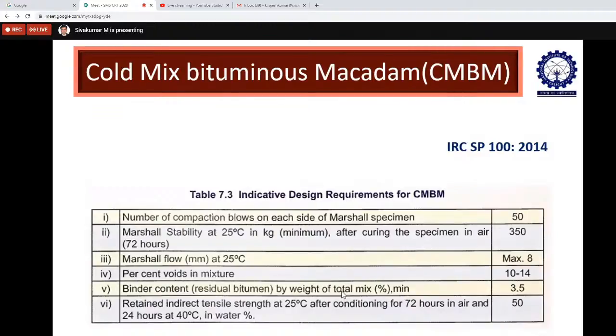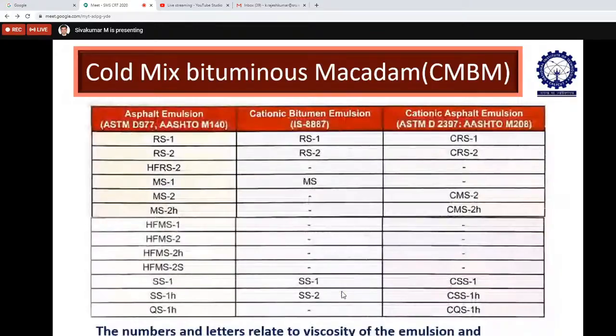Whereas for cold mix at 25 degrees C, the maximum is 8 mm. Okay, and the air voids percentage is one of the important factors in CMBM. If you see, for the dense graded mix we take it as 3 to 5%, whereas here it is 10 to 14%. And the binder content, that is not the emulsion content but the residual bitumen content after settling, should be a minimum of 3.5%. Okay, so these are the design specifications as per IRC SP 100 2014.